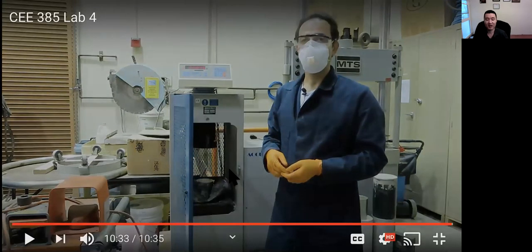Okay, so what Reza said is very clear. Remember the fracture surface. For this normal concrete, the fracture surfaces basically go around the ITZ. So the aggregate itself does not crack, does not get damaged. So let's go back to the weakest link series we talked about earlier. For normal concrete, the weakest link is the cement paste and ITZ. So the aggregate is strong and is not touched. And just follow what he said about how to calculate the compressive strength and do the curve.